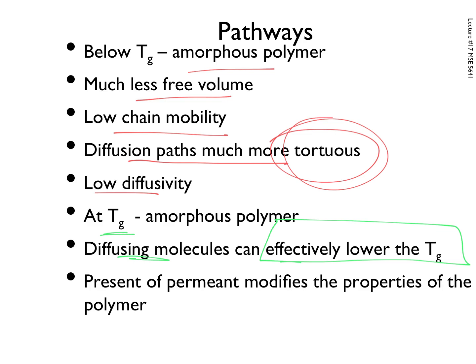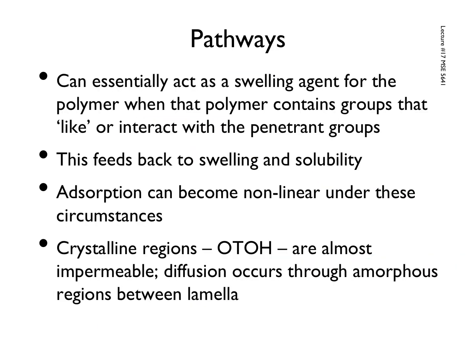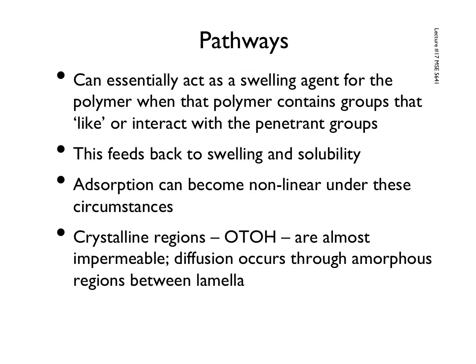All right, so the presence of the permeant modifies the properties of the polymer and drives this nonlinear change in the diffusion coefficient, which makes plastics very different from metals. Essentially it acts as a swelling agent for the polymer. When that polymer contains groups that like or interact with the penetrant groups, it gives you a feedback loop for swelling and solubility. Adsorption can become nonlinear under these circumstances, and this is how we see things like PMMA sucking up a lot of CO2. In contrast, however, crystalline regions are almost always impermeable.